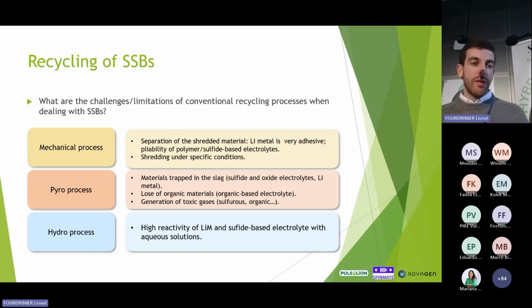Now, what are the challenges or limitations of conventional recycling processes when dealing with the next generation solid-state batteries? So first, for the mechanical process, as I have explained, we have some elements that are reactive in the solid-state batteries. So we need to control the atmosphere of our mechanical process. In conventional processes, the shredding is done under inert atmosphere of nitrogen, but the nitrogen is also reactive with lithium metal. So you have to ensure that you have a dry and inert atmosphere for your material.